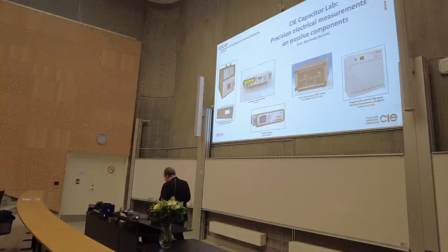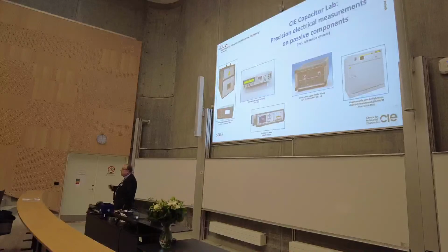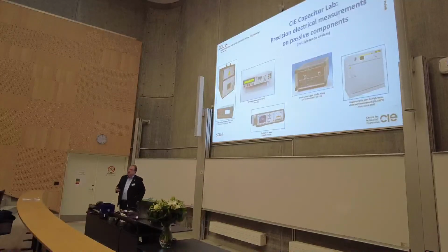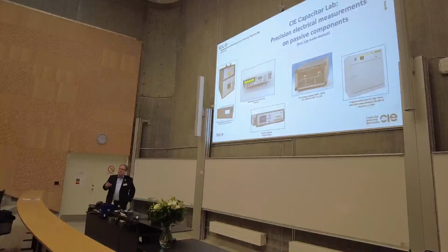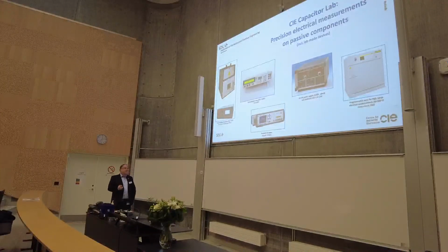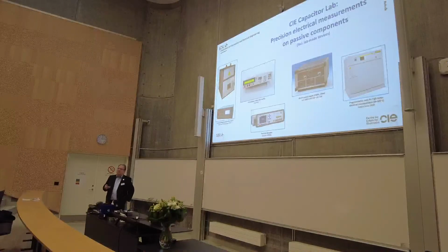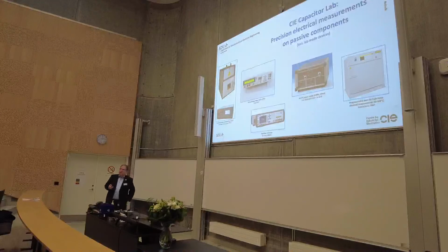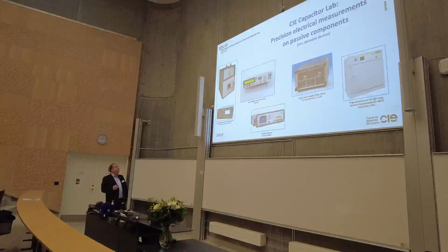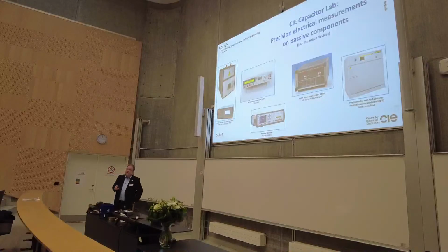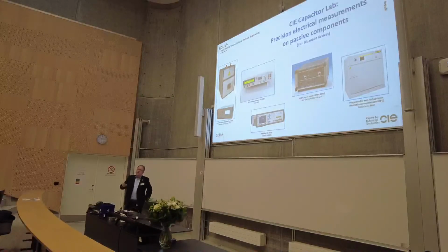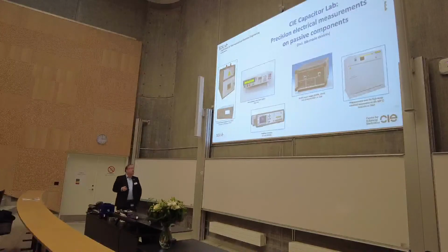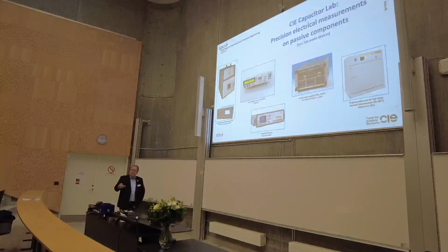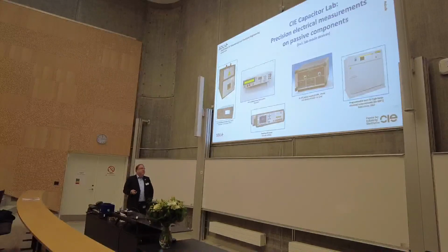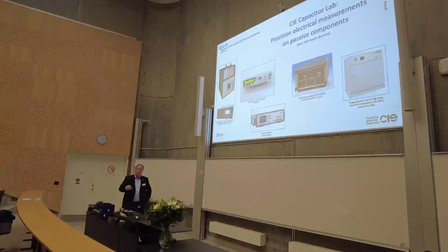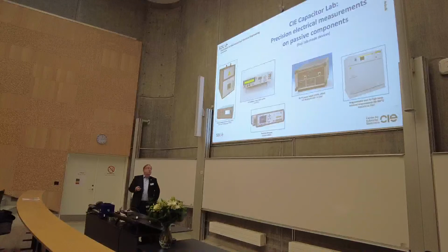Yes, another thing which is quite important is breakdown testing, because we are exposing power electronics to higher and higher voltage levels, and that means that insulation materials must also withstand higher external voltages. And we have to understand how those insulation materials behave under such high field conditions. Therefore, we have the chance to use a so-called partial discharge tester. That means we can see how many coulombs, for example, are bypassing a dielectric under such conditions, and we can also expose such polymers to thermal deterioration reactions beforehand and see how partial discharge is influenced under these load conditions.